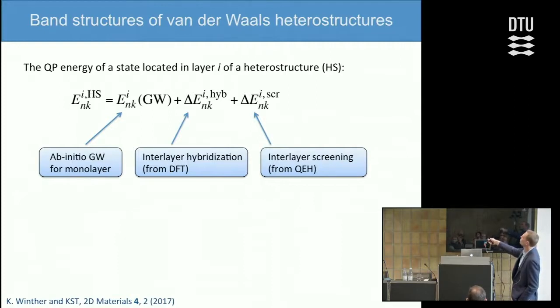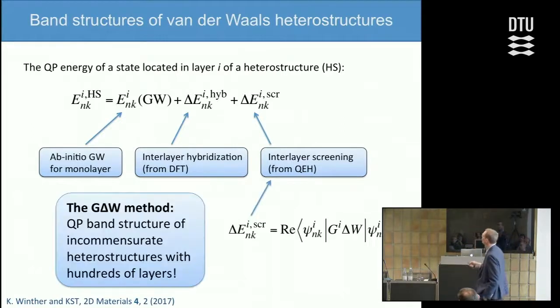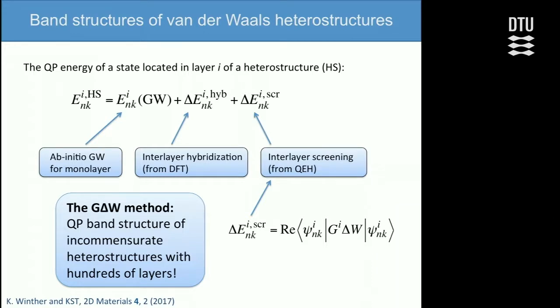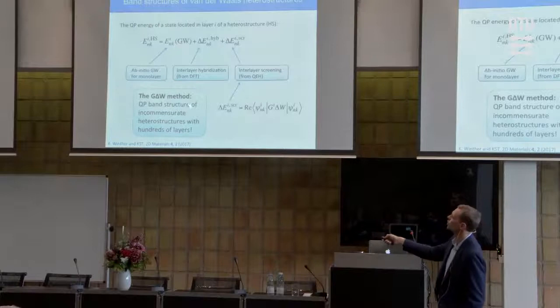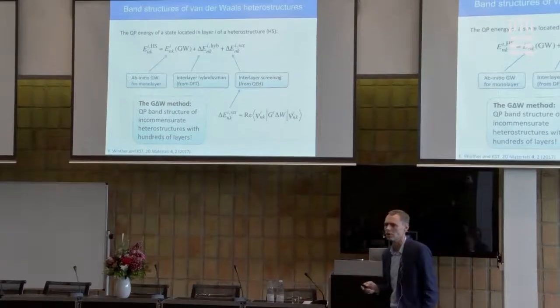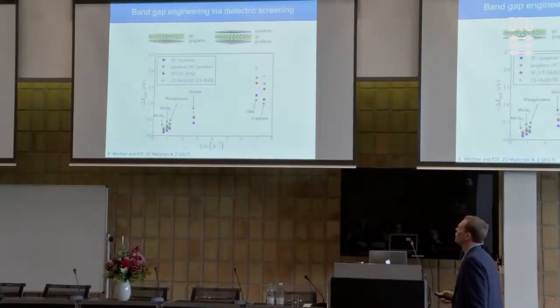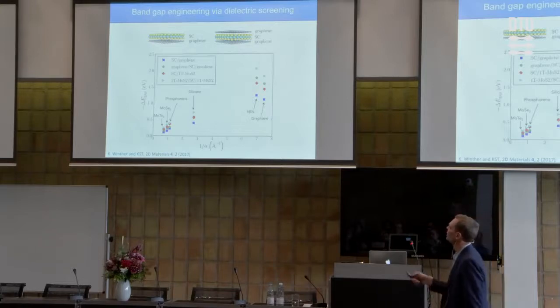There's also a correction due to the screening effect, which is much more complicated, but we can calculate that using the QEH model, because we can calculate the change in electronic screening between the electron and the other electrons in the system. So we can do that very cheaply, and that leads to the G delta W method we've developed, which allows us to calculate quasiparticle band structures of heterostructures with hundreds of layers. I think that really opens up new perspectives in the field.